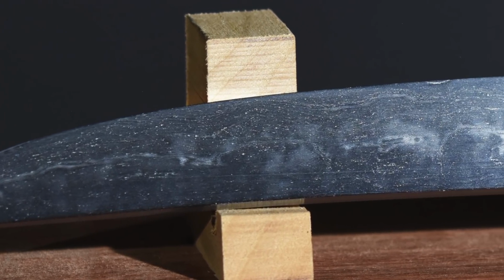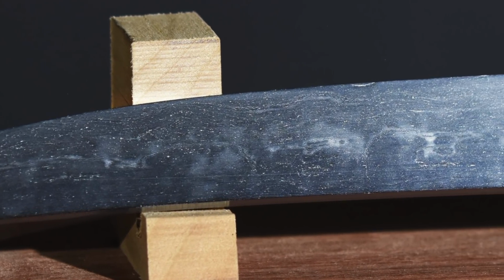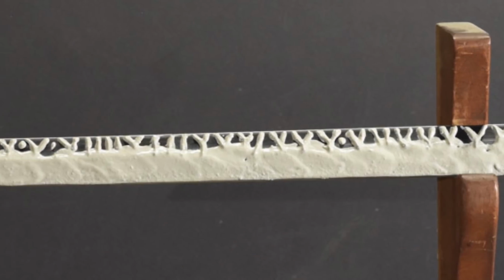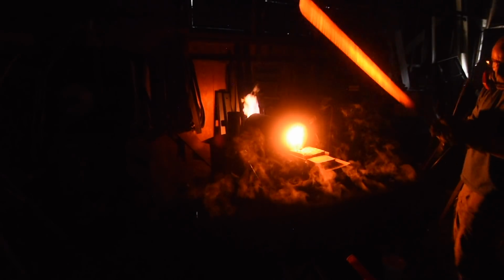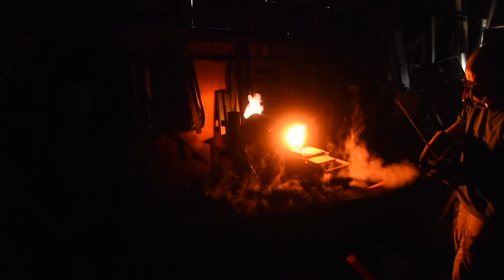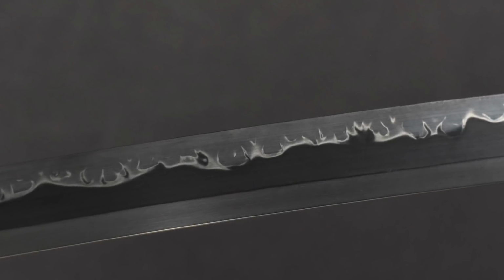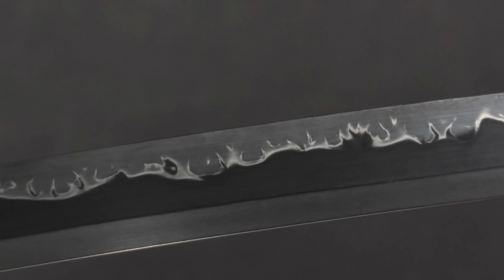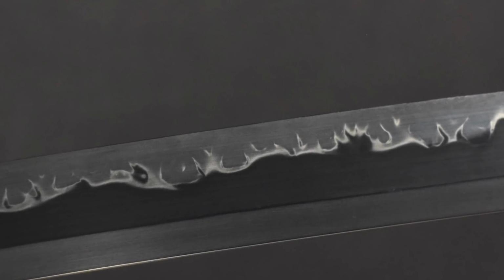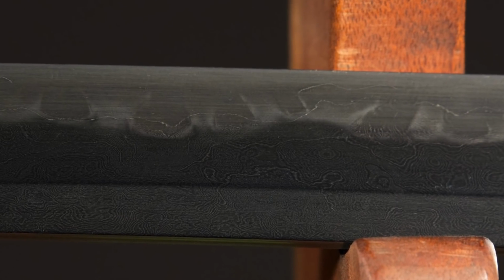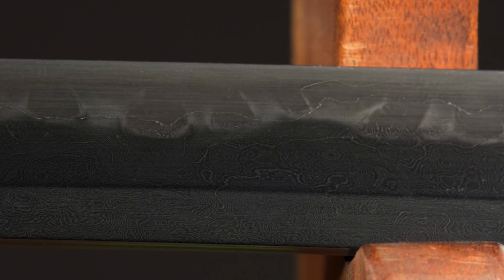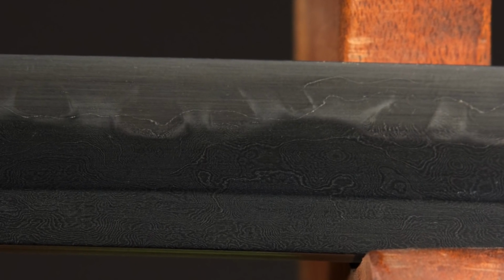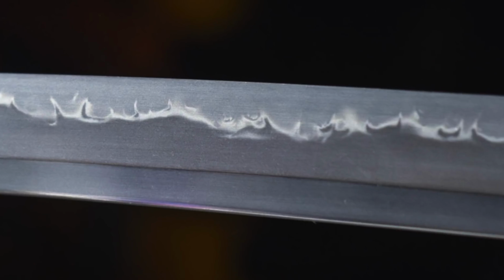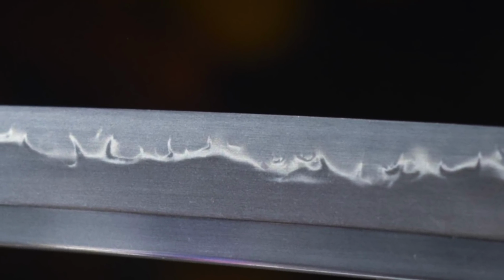As most of you probably know, hamons are typically formed by coating the blade with clay prior to quenching. Where there's clay, the blade cools slowly and the blade fails to harden. Where the blade's exposed directly to water, the steel does harden. And the hamon's just a visual representation of the structural difference in the steel between the hard portion, which is martensitic, and the soft part, which is formed by pearlite.